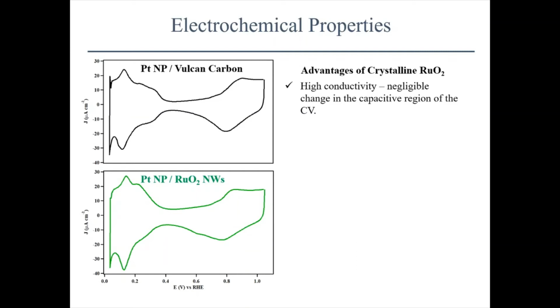And if you look at these cyclic voltammograms, in addition to the traditional features where we have the hydrogen adsorption region of platinum and the oxide region of platinum, we can compare this intermediate mid-region, which is the capacitive region, and this should tell us a little bit about the conductivity of the catalyst and the effect of the substrate. So what we saw was that even though we were using an oxide, the capacitive regions were pretty similar. So we were not seeing this dramatic capacitive effect from having a metal oxide due to low conductivity. So in essence, the conductivity was pretty similar.